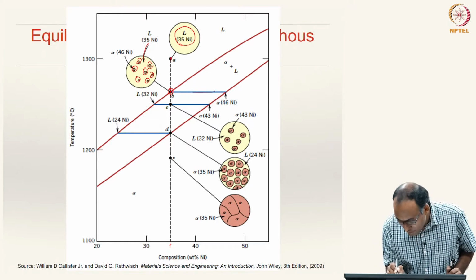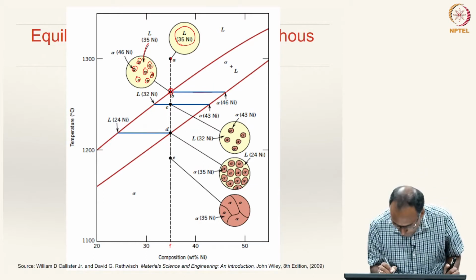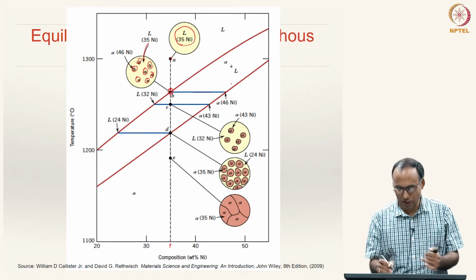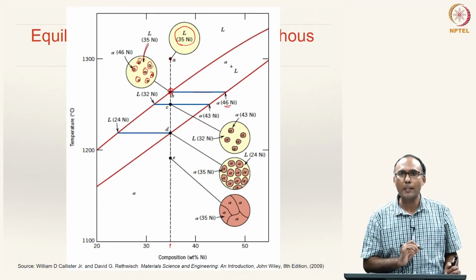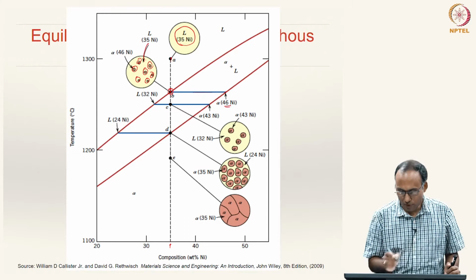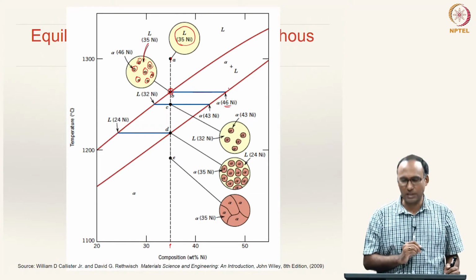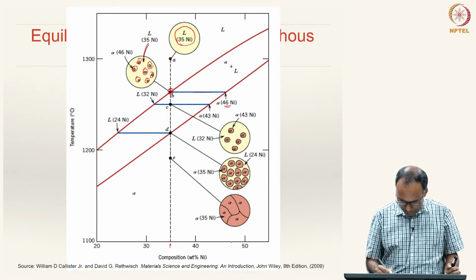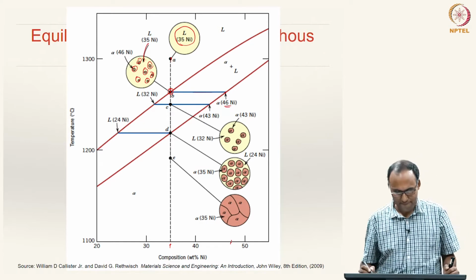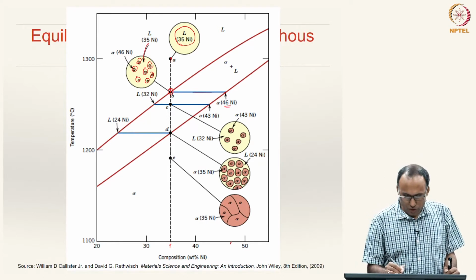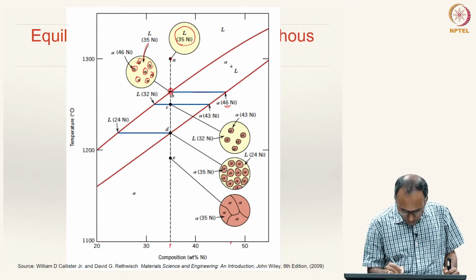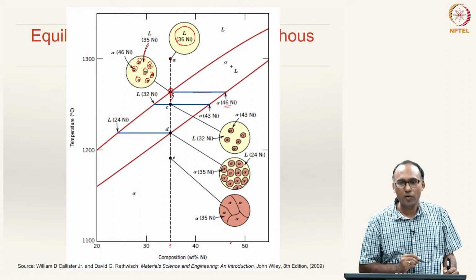because you are at the very beginning, the liquid phase composition will be almost the same as the original composition, that is 35% nickel, that is what is shown. But on the tie line, whatever initial solid is formed is very rich in nickel. So, that is 46% nickel, right. You can see this is 46% nickel. So, if you draw a vertical line, that corresponds to 46% nickel. All right. So, you enter the two phase region, and then if you further cool it down, what happens?